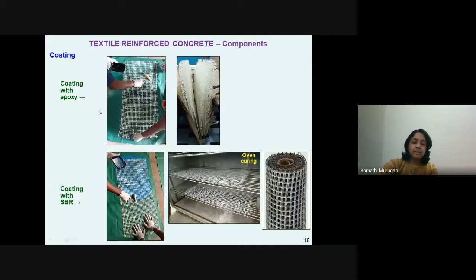Here I've shown some pictures where in the first image, what we see is the coating of textiles with epoxy. All of these procedures we have done in our laboratory, and we have tried the coating and development of the corresponding textiles. So what we got was the uncoated textiles from one of our partner institutions from Germany, and we tried coating it with the essential epoxy component.